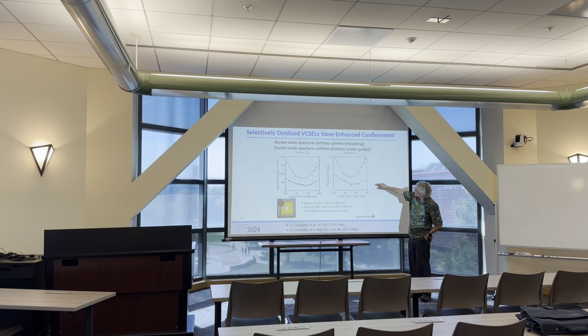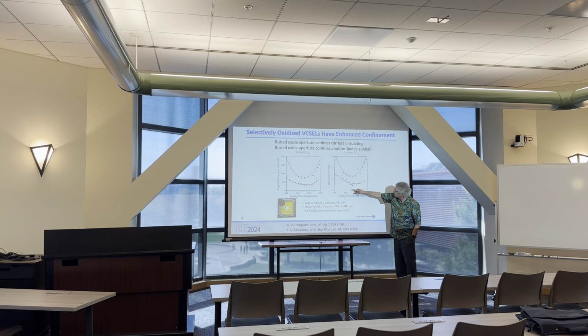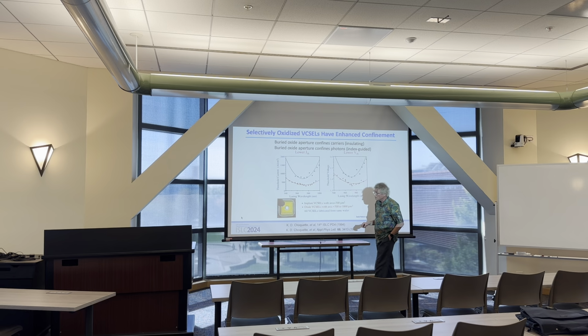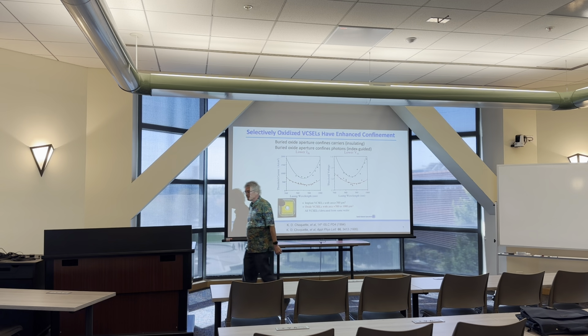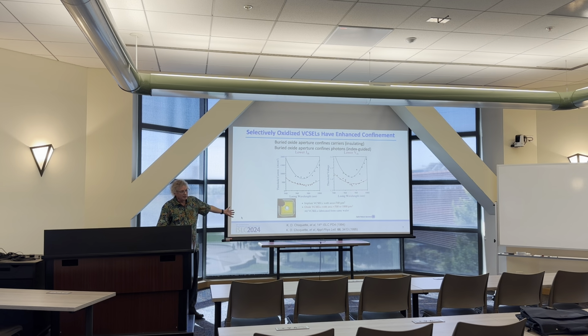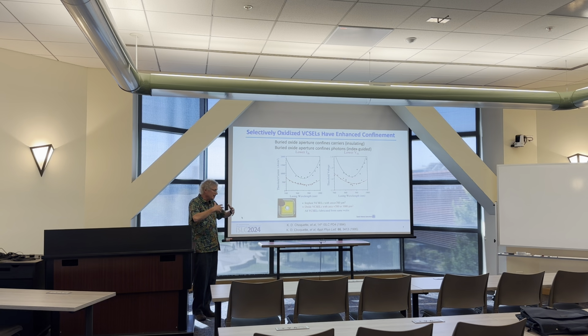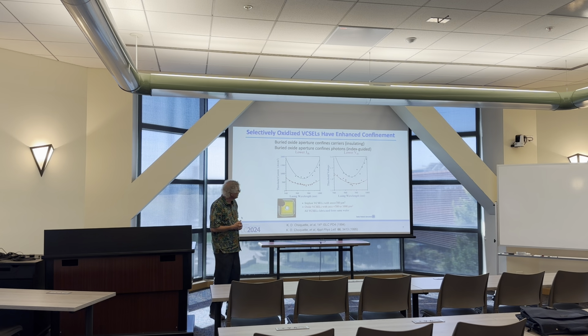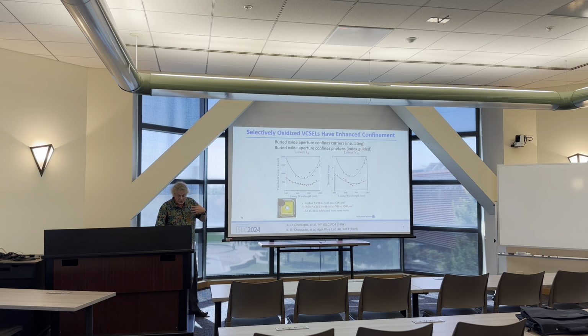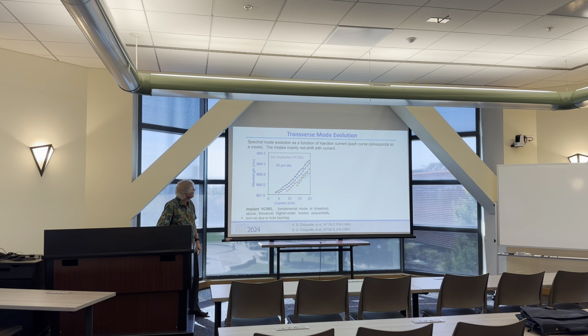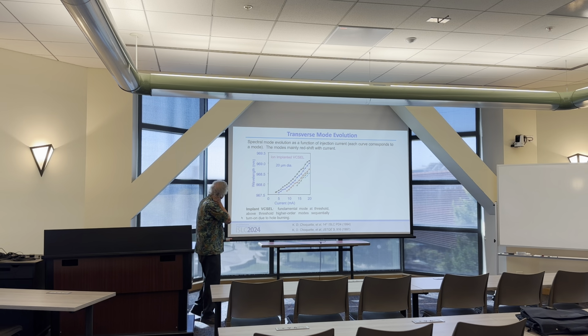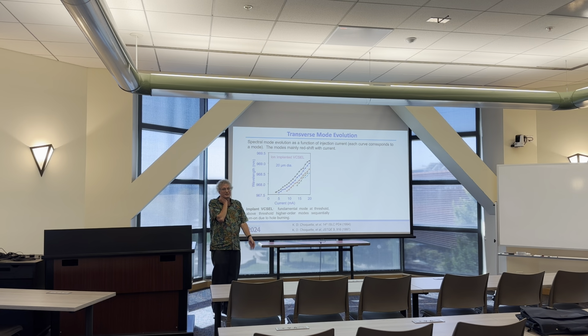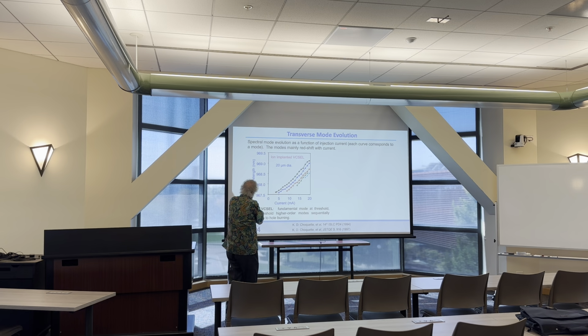This is the threshold voltages, and I mentioned some of these points here are only less than 100 meV above the photon energy. And that's coming about because the oxide aperture provides both index confinement and electrical confinement, which the implanted structure didn't. And then the other data that I showed, which is amazing, I keep showing this after 30 years, is this. If you take my 572 course, you'll see this in class.